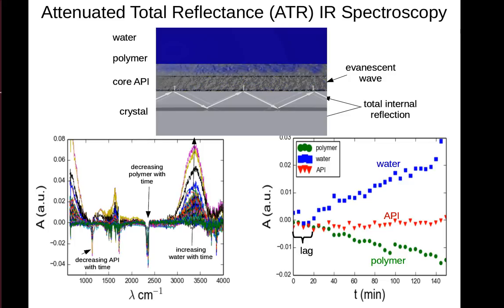If we look at the spectra, we see that in the wavelength range of water, we see a growing absorption intensity, and thus that is the measuring of the water as it gets close to the crystal surface. At the same time, we see a decrease in the signal of the polymer as it is dissolved and most likely being brought up further out of range from the evanescent waves. And we also see a decrease in the absorption intensity of the API material.